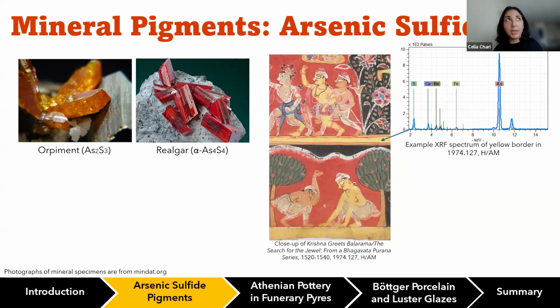And there was the unfortunate, common misidentification of assuming that an arsenic containing yellow pigment is orpiment, or an arsenic containing red pigment is realgar, without any additional analyses that can give information on structure like X-ray diffraction or Raman spectroscopy.